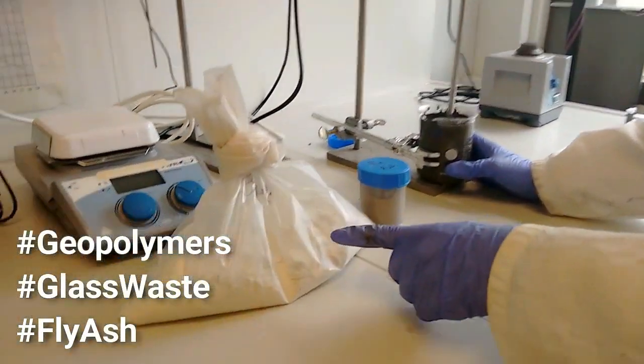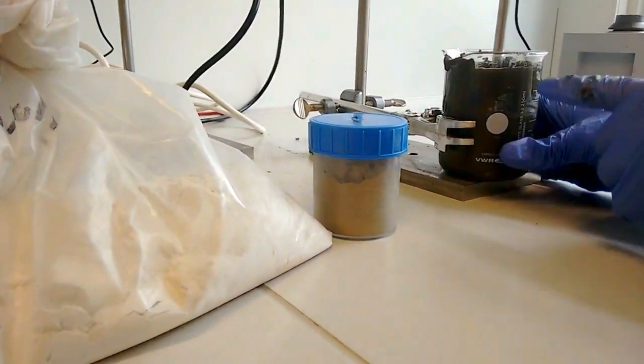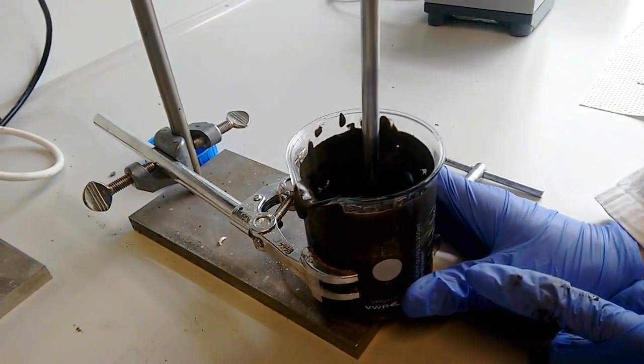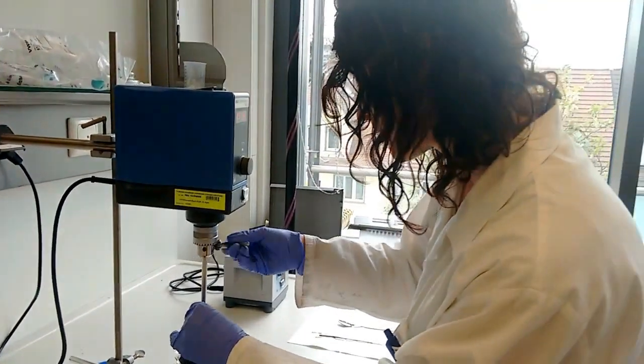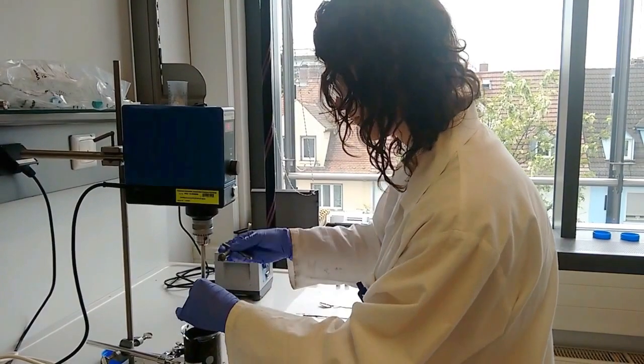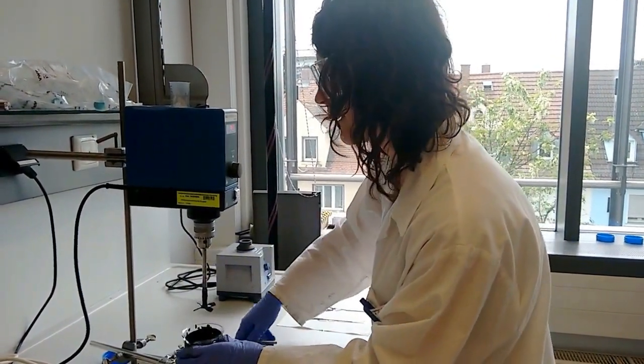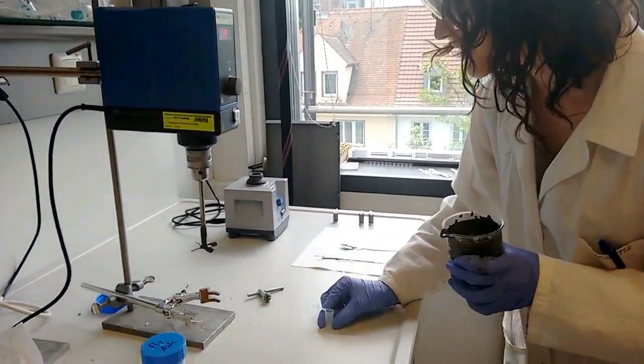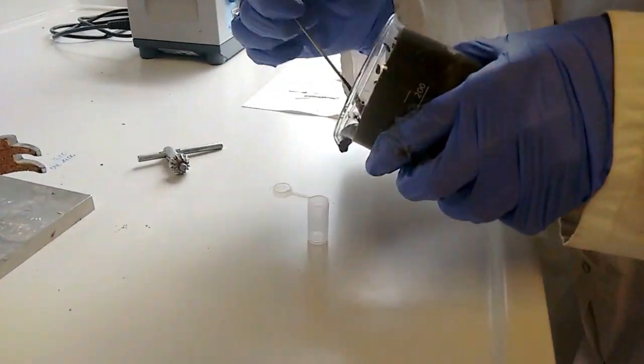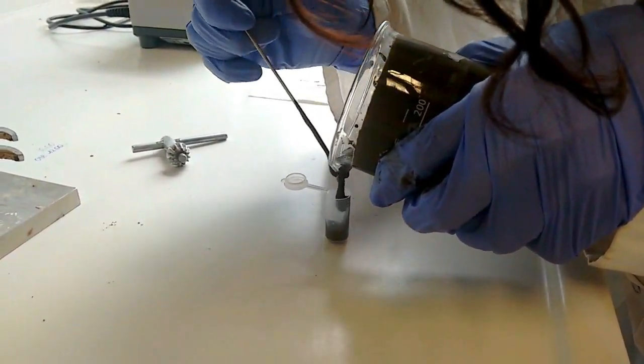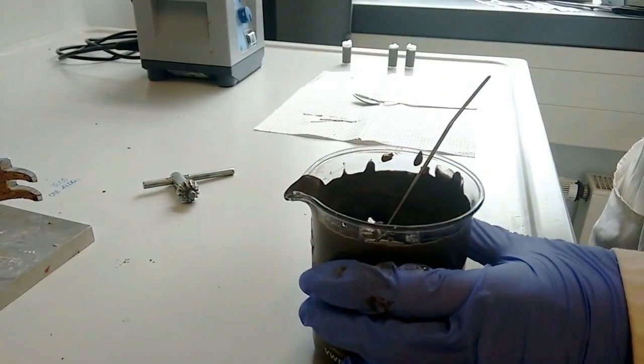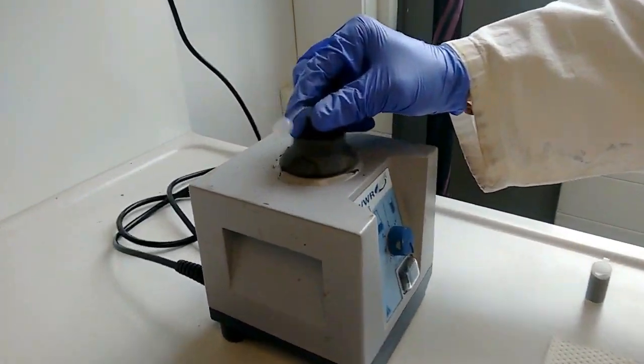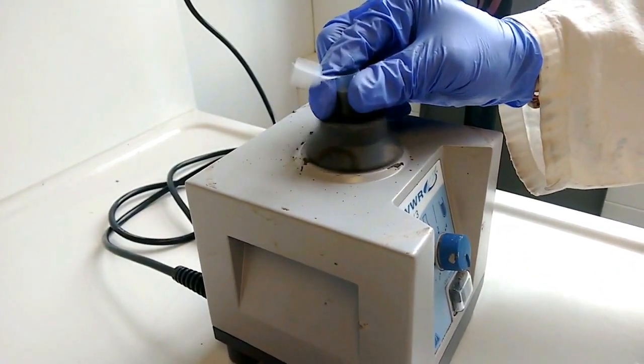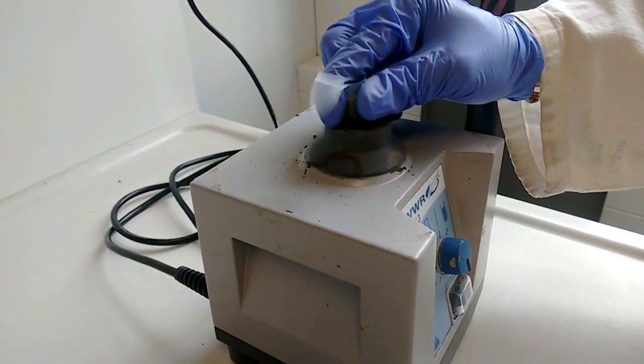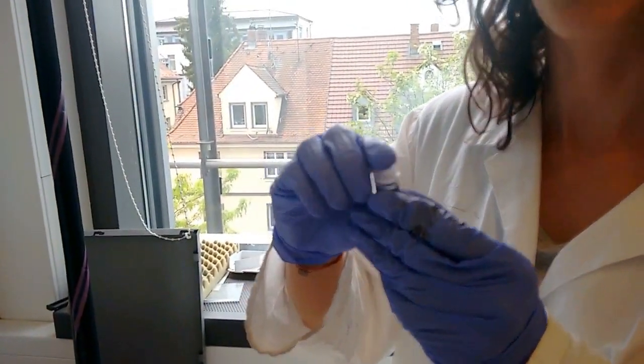Starting from the raw materials, glass waste and fly ash, we are mixing everything together with sodium hydroxide for 4 hours. After that, when the slurry is homogeneous, we can cast it in polyethylene molds. We are vibrating our material with a vortex to take out the bubbles. So after that, the geopolymer is ready and we can put it in the oven for the curing.